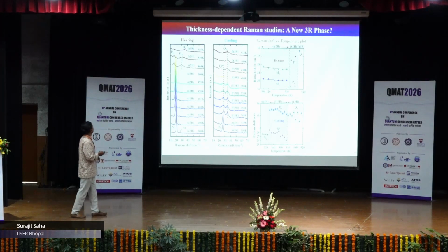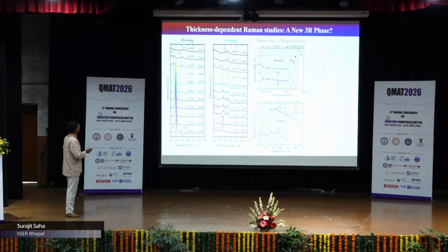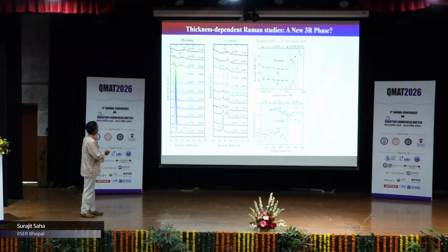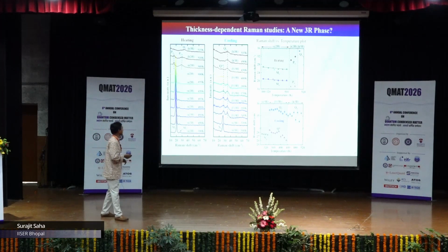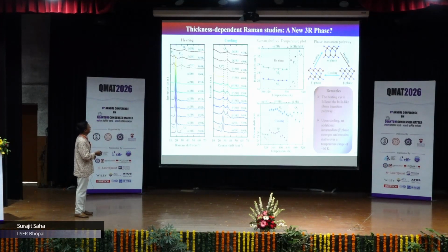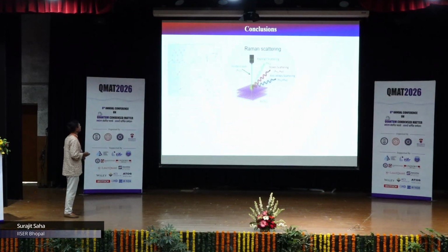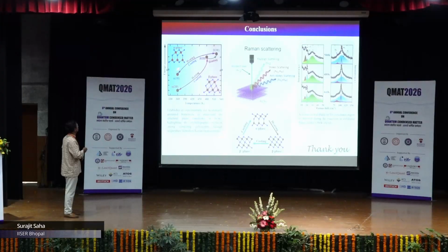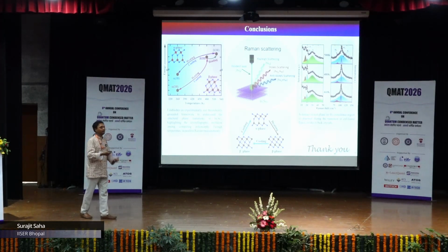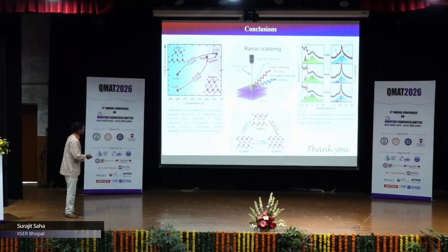Then we did another round of experiments, which is also an interesting aspect. When we did this on a thinner flake, going from alpha 2H to beta 3R and then cooling down, we saw that there is an intermediate phase for some thinner flakes that happens to be the beta prime phase, and that's different from the structures that I was discussing. The beta prime phase, we believe, is another distorted octahedrally coordinated structure of this system. So I'm concluding this part: we have a reversible or irreversible transition depending on the temperature limit that we push it to, and these are the different structures that come out.